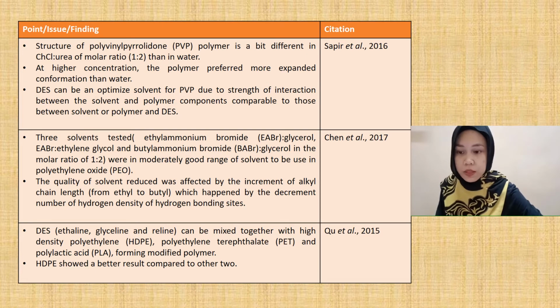Sapir et al. 2016 mentioned that DES can be an optimized solvent for PVP due to the strength of interaction between the solvent and polymer components being comparable to those between solvent or polymer and DES. It is due to the structure of the PVP polymer being a bit different in ChCl-urea of molar ratio 1:2 than in water, which indicates that at higher concentration, the polymer prefers a more expanded conformation than in water.